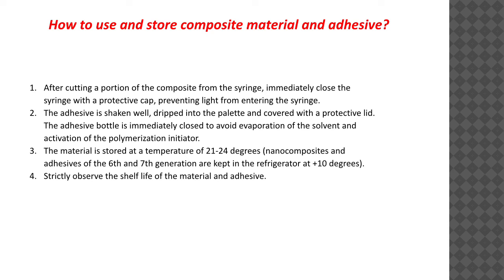How to use and store composite material and adhesive. After cutting a portion of the composite from the syringe, immediately close the syringe with a protective cap to prevent light from entering the syringe. The adhesive is shaken well, dripped into the palette, and covered with a protective lid. The adhesive bottle is immediately closed to avoid evaporation of the solvent and activation of the polymerization initiator.